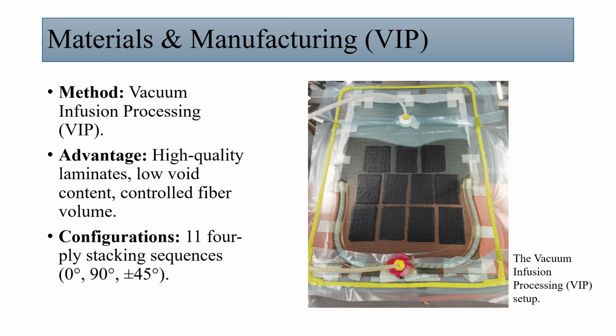To ensure high-quality test specimens, we utilized vacuum infusion processing, or VIP. Unlike basic hand layup, VIP allowed us to produce laminates with minimal void content and consistent fiber volume fractions. We manufactured 11 distinct 4-ply stacking sequences, strategically combining 0, 90, and plus-minus 45-degree orientations. This variety was essential to study how pure axial, pure transverse, and complex off-axis layups behave under flexural stress.